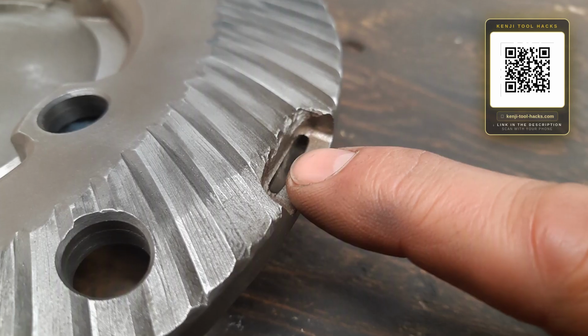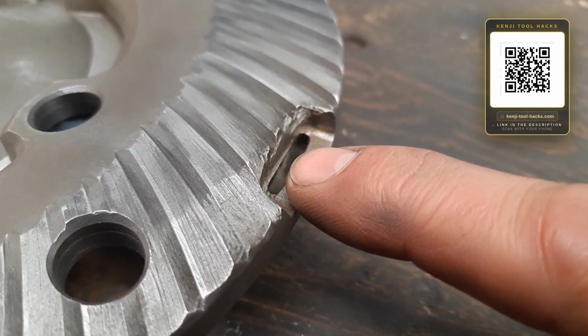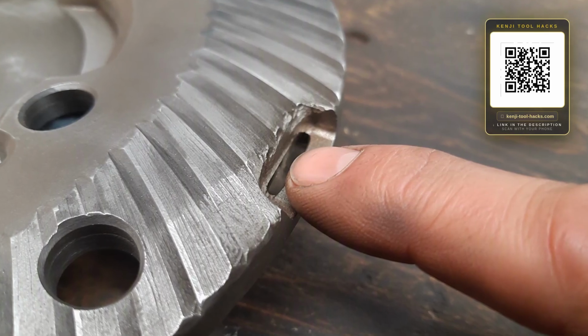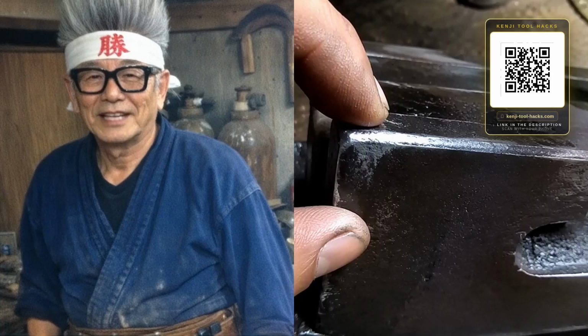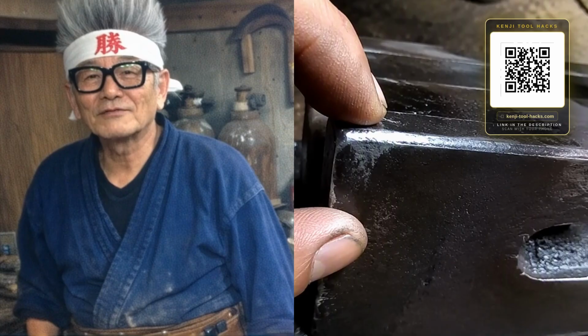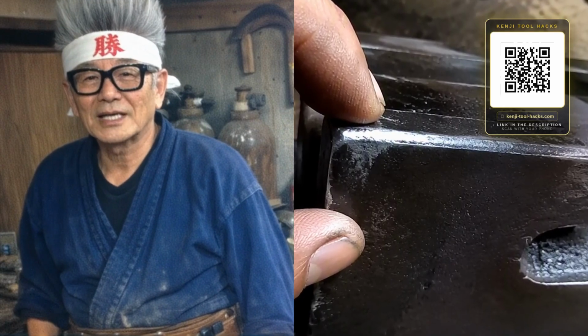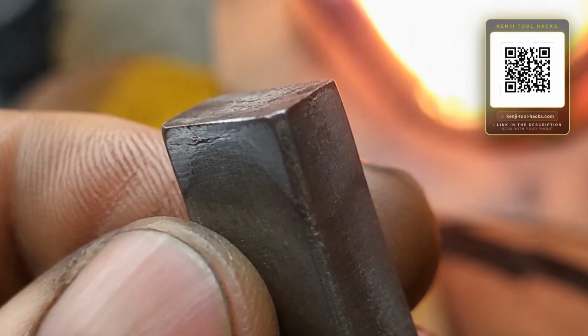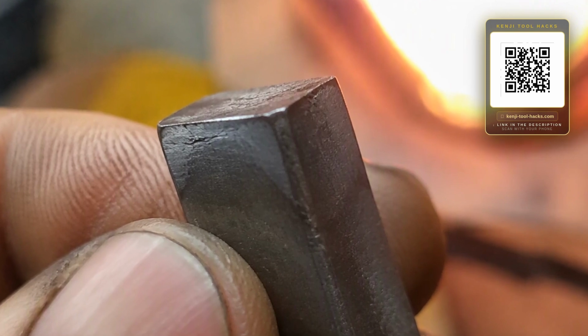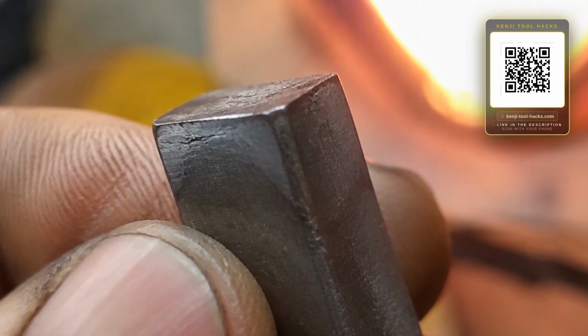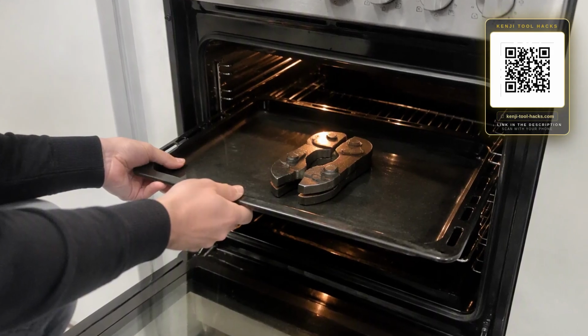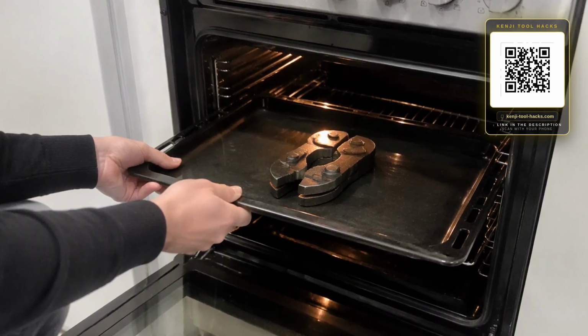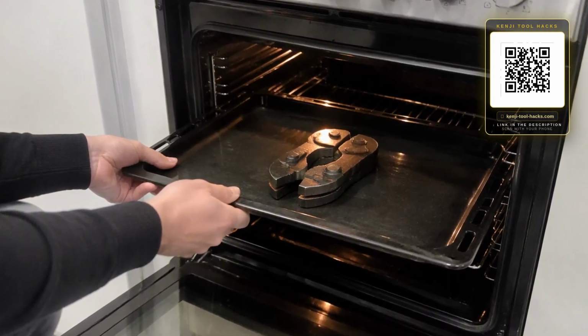There is one more step, and skipping it is the mistake I made the first time, which is why I chipped an edge even after I hardened it. Fresh out of the quench, that martensite edge is glass hard and brittle, so full of stress it can crack if you look at it wrong. You have to temper it. Put the whole jaw in your kitchen oven at about 400 degrees Fahrenheit for 1 hour. Then let it cool in still air.